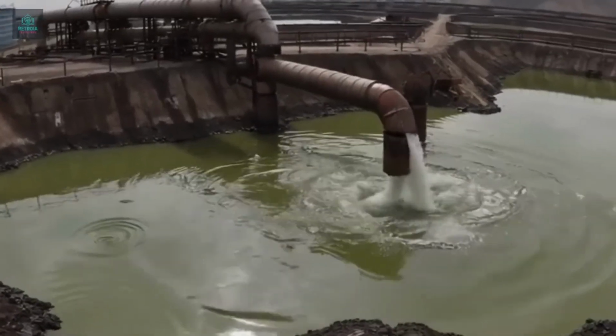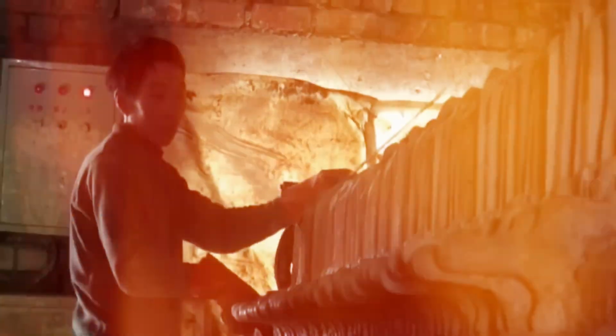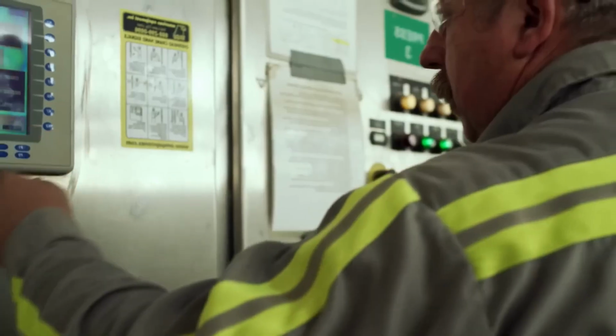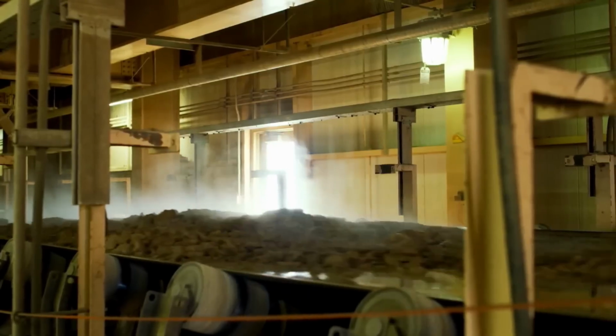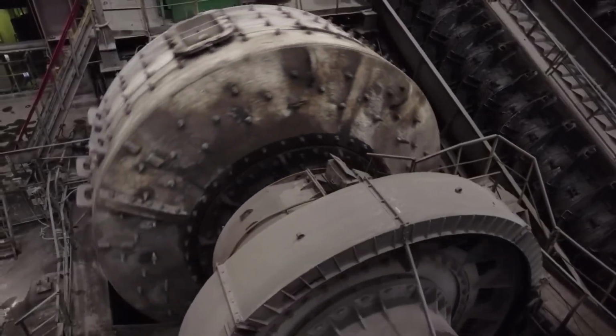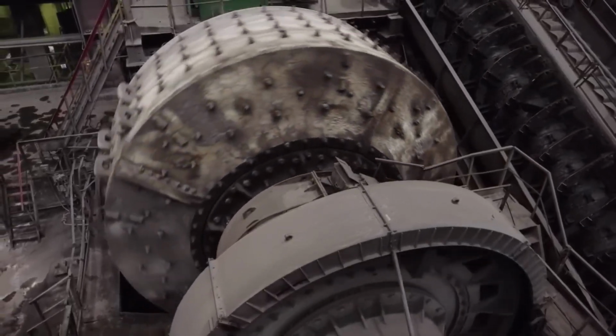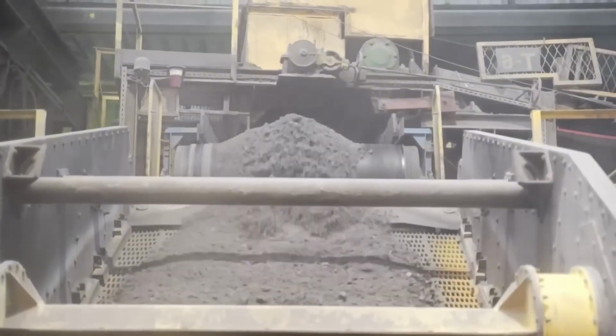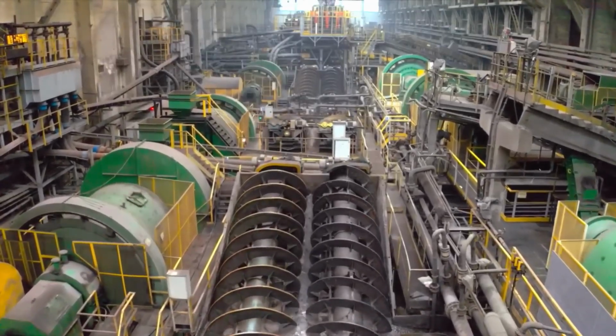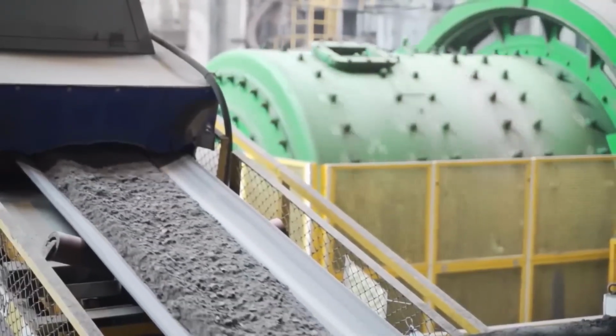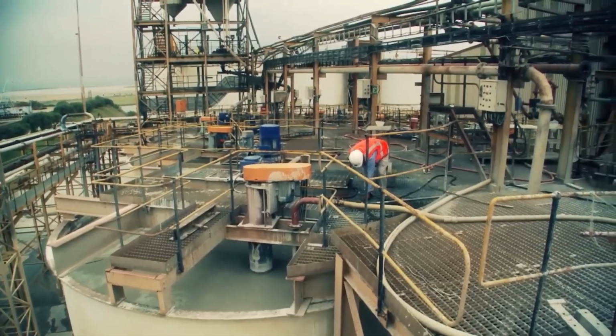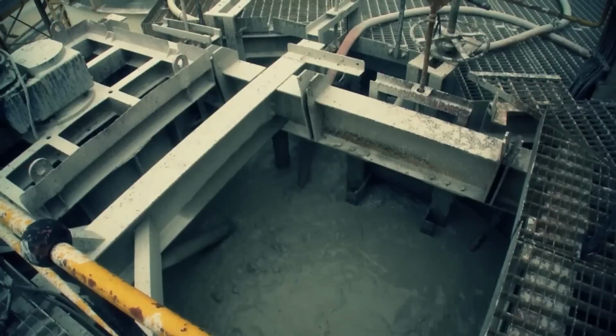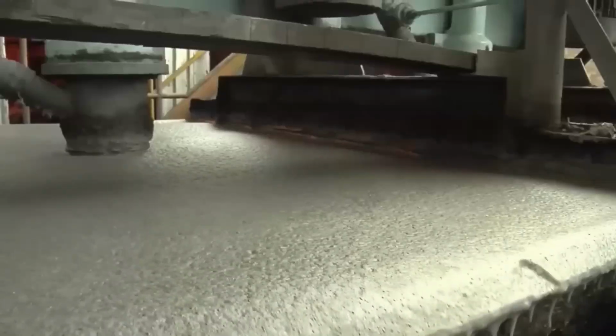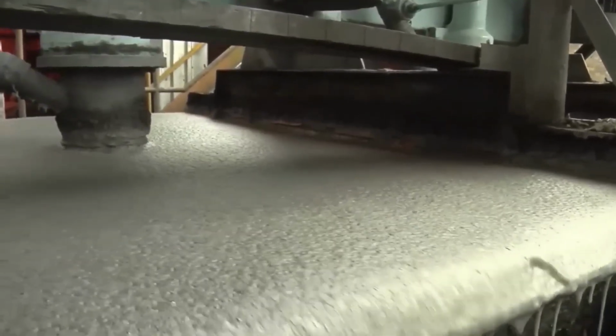The mineral undergoes a leaching process where it is mixed with acids such as sulfuric acid. This action dissolves the rare earth oxides, including neodymium, forming an aqueous solution that contains dissolved ions. The resulting solution contains a mixture of several rare earth elements with very similar chemical properties. To separate them, a technique called solvent extraction is used. An organic solvent is added that selectively extracts certain ions. Through multiple stages of contact and washing between the aqueous and organic phases, the different elements are separated one by one.